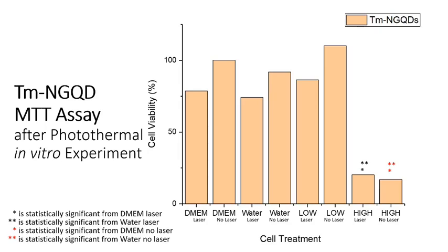What we also notice with the thulium is that actually our low with no laser has more than 100% viable cells. And the reason why it has that high number there is because, as I said before, we're using the control to determine what is the 100% viable cells. So when we see that this has more, that tells us that it did better at surviving than the DMEM with no laser treatment. And what we think is the reason behind that is because glucosamine is the precursor for NGQDs, that it was using that sugar in it to break it down and to feed the cell, so it was actually helping its growth in this low toxic state.